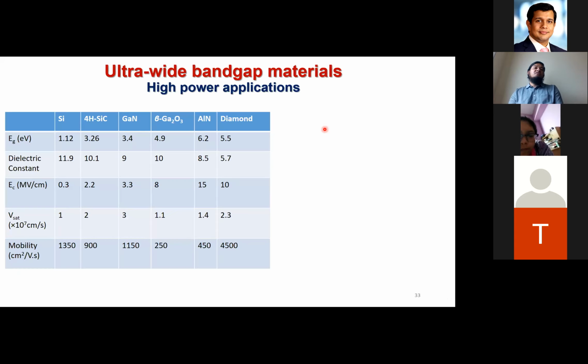As it happens, silicon carbide and gallium nitride are not the only wide bandgap materials. There is a new family of semiconductors, so-called ultra wide bandgap materials: beta gallium oxide, aluminum nitride, or even diamond, where the band gap ranges from 4.9 to 6.2 electron volts. They also have very decent mobility and other parameters. Everyone in the community is pretty excited, and there is a lot of effort going on to make high power, high frequency devices based on these new materials.